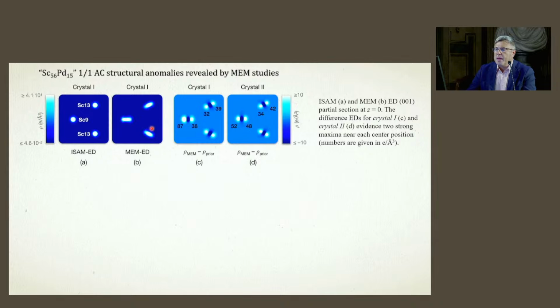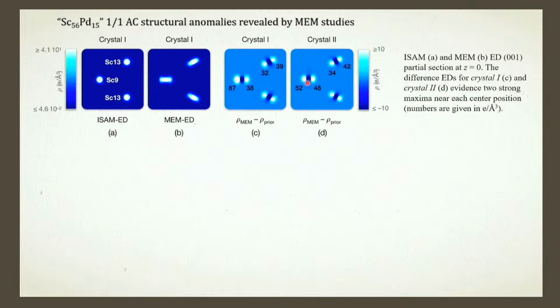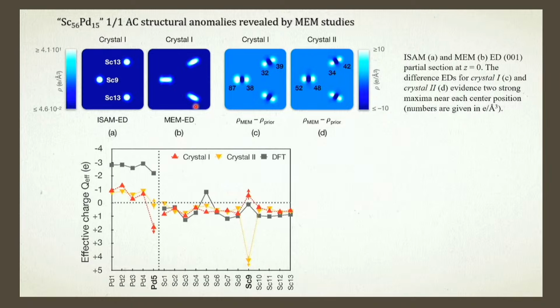We constructed some difference maps just to highlight that for two crystals, the scandium-9 positions behave somewhat differently. What is more, some difference plots were constructed for charge evaluation of different species, also compared by DFT calculations.